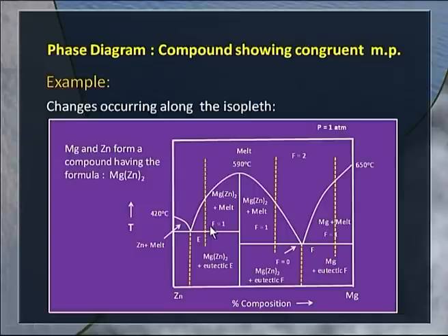Whatever solidification sets in takes place at constant temperature, and then ultimately when the entire melt has solidified, the temperature decreases and we are left with only solid phases. And you can see the solid phases that we have. In this case, the primary crystals of zinc, which had time enough to grow from here to here, and then a solid that separated out corresponding to the eutectic composition, an intimate mixture of zinc and the compound Mg(Zn)2.